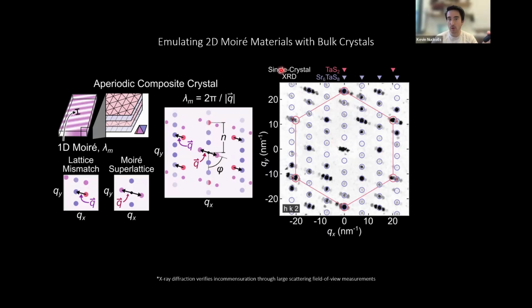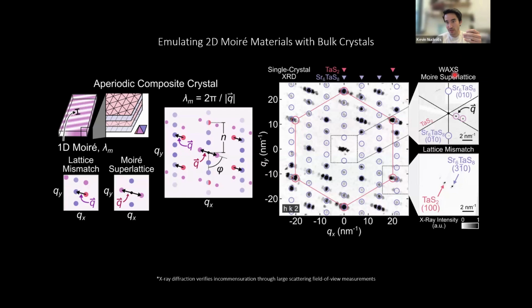So we first start with single crystal X-ray diffraction because it allows us to verify out to many, many Bragg zones that the monoclinic and hexagonal layers are atomically incommensurate. They don't ever line up out to many, many Bragg zones. But we then use a higher resolution X-ray diffraction tool called wide-angle X-ray scattering, which is higher resolution, but it's more myopic. So I can't see quite as far in momentum space.